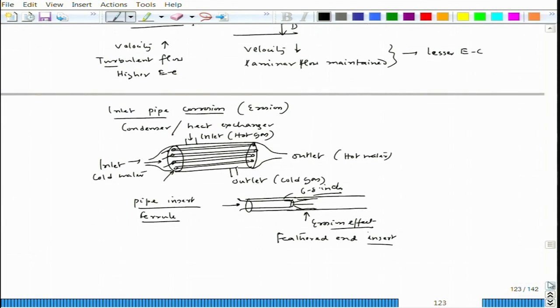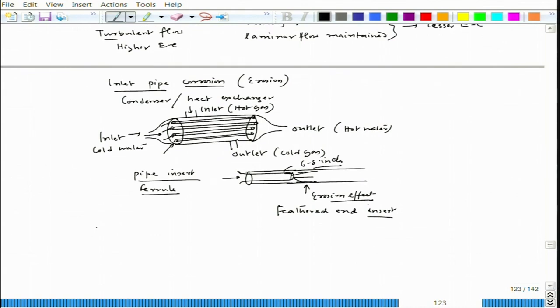Okay. So this is another particular instance one can think of. Now, this is a design part, there could be the possibility of deaeration or addition of inhibitor, fine, because of the high speed. The inhibitor can be taken to every place and then corrosion protection can be obtained. Okay. Then temperature. Temperature can be reduced so that the erosion corrosion effect can be controlled to a great extent.